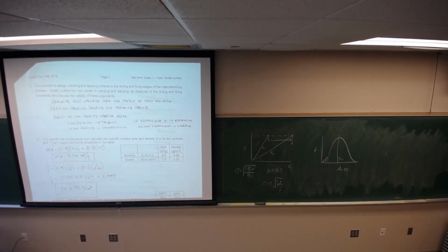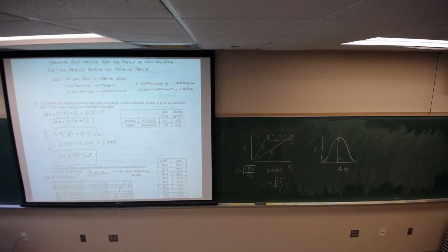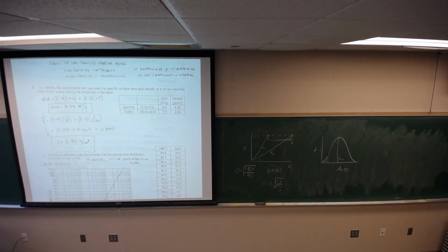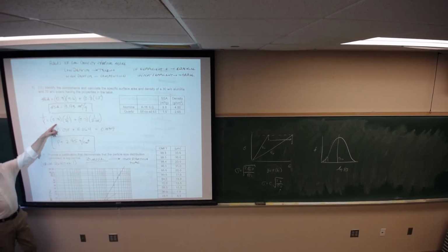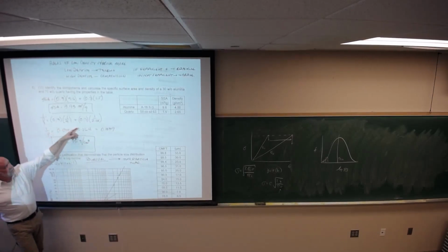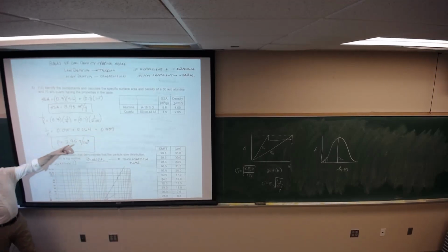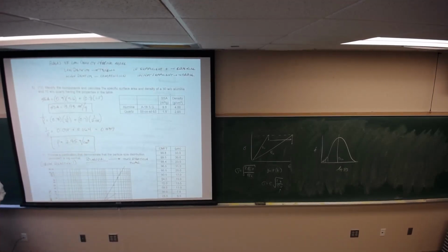Okay. This question here, number 6. Identify the components and compute specific surface and density of 30% alumina, 70% quartz, given the properties in the table. So it's very straightforward. Since you do surface area on a mass basis, 0.3 times 9.6 plus 0.7 times 1.5 gives you 3.93 meters squared per gram. And then to do density, it has to be the mass fraction times 1 over the density plus the mass fraction times 1 over the density. That works out to 0.339. 1 over 0.339 is 2.95. So I hadn't approached it that way before. That was good.